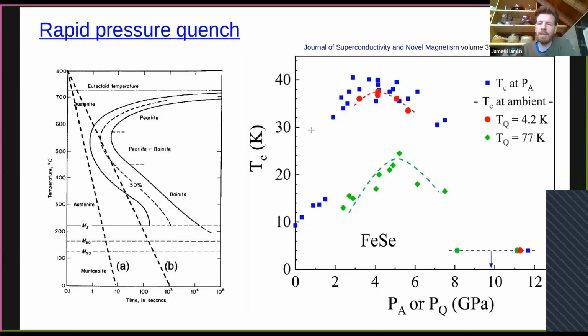And here's an example he showed for the TC of iron selenide, where the blue data points here are TC under some applied pressure, right? And the red and green points are the TC that he gets at ambient pressure after quenching from the pressure shown on the phase diagram here. So if he quenches from 4 GPa at 4.2 Kelvin, he rapidly reduces the pressure. They can bring the TC, this high 40 Kelvin TC that's normally only observed at high pressure, all the way back to ambient pressure. And so this approach of very rapid pressure changes, I think, shows a lot of promise, and I think this is something we'll hopefully see more of in the future.